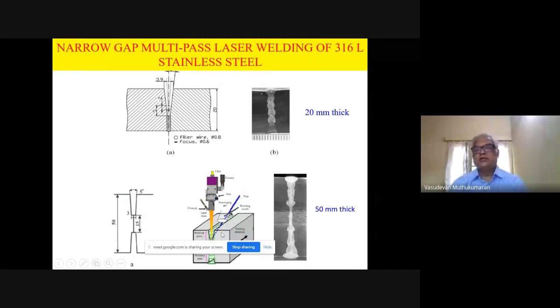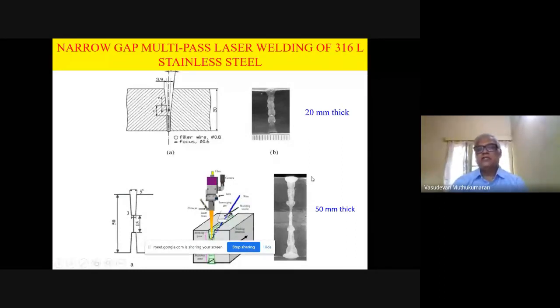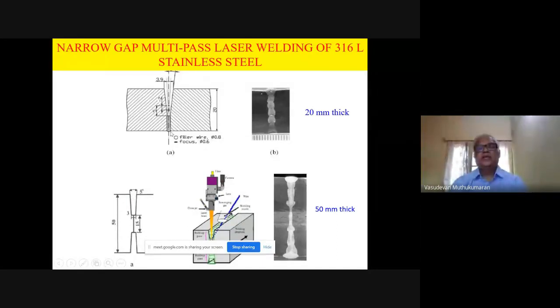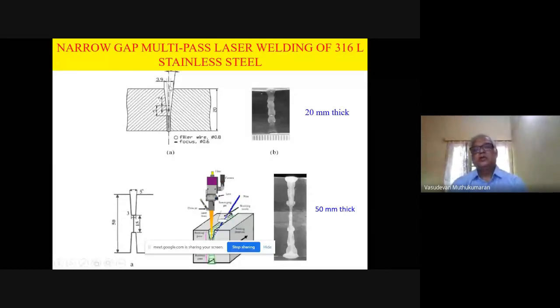You can see the cross section. With the minimum number of passes, they could weld using this kind of groove. Here you can see 20 mm thick could be welded. This is the root side and then the top side. Again, the cross section is shown. By multi-pass laser welding, they could demonstrate this.